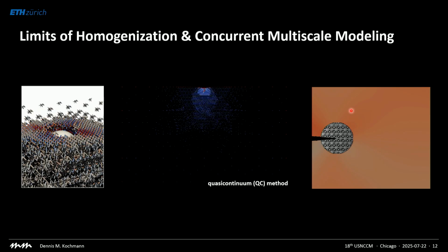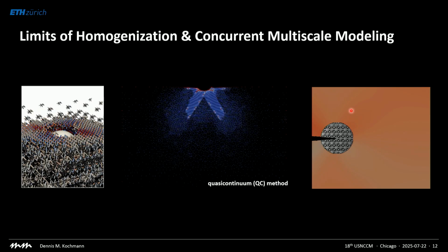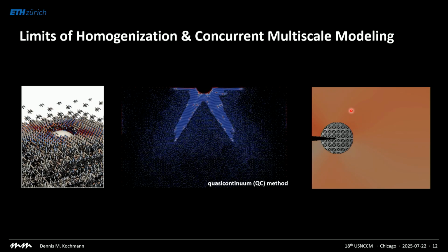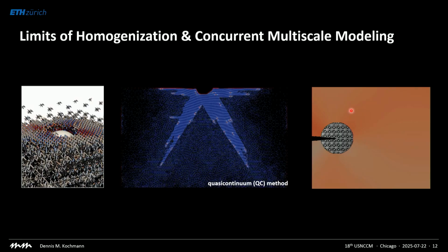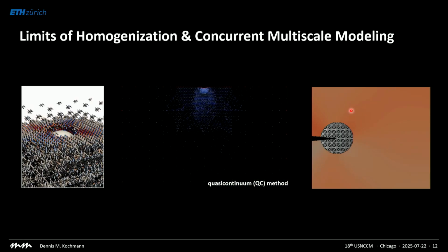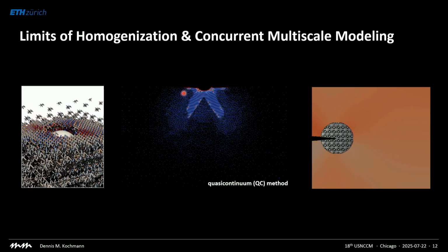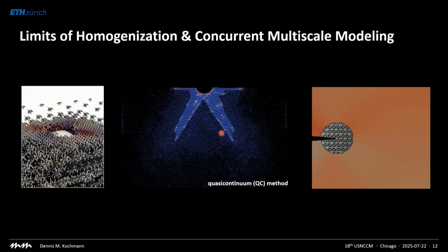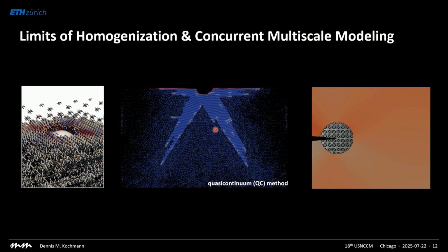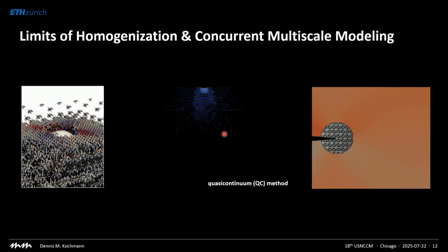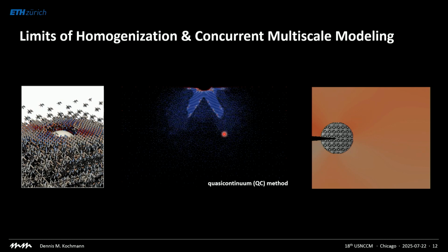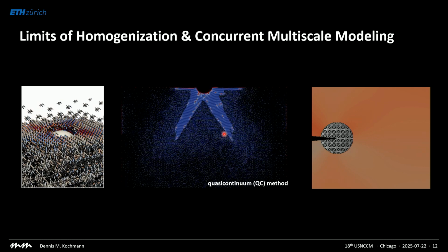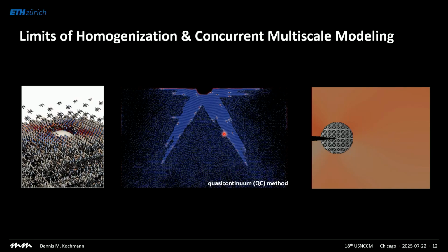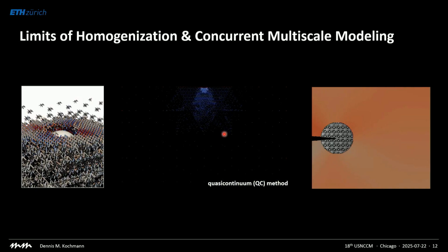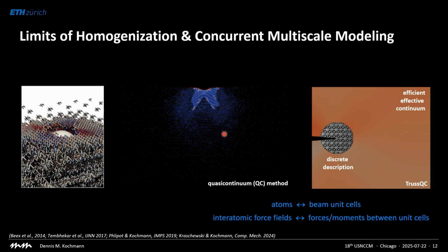And of course, here we can borrow from atomistics, for example. There's a technique called quasi-continuum, or QC, that was again developed more than 20 years ago to have full atomistic resolution where you need it, adaptively tracking down, for example, dislocation events, but efficiently coarse graining elsewhere to gain efficiency. In atomistics, let's be honest, this is not a widely used technique because it only works at low temperature, only for crystalline solids. It has a lot of limitations. But for trusses, this works beautifully.